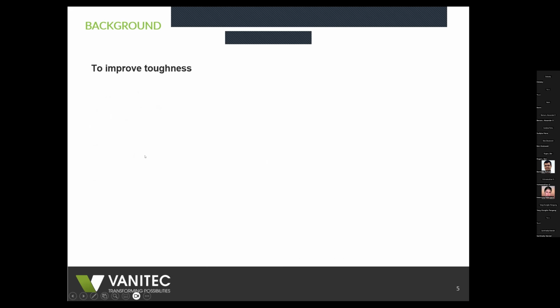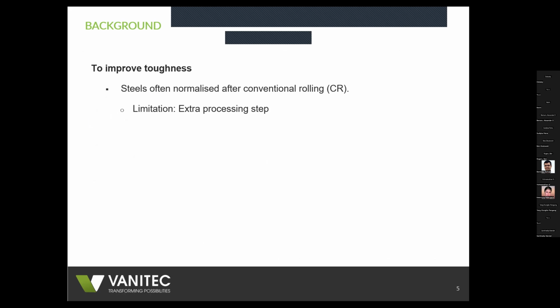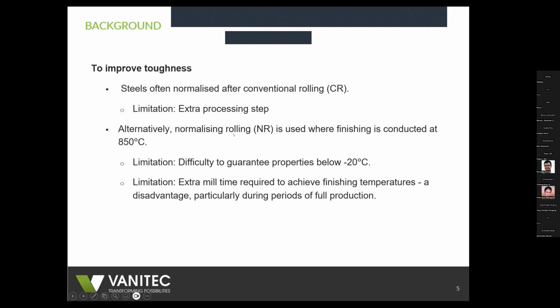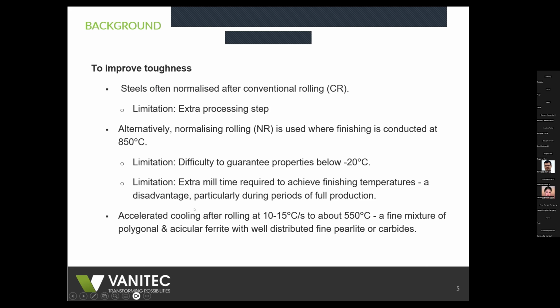You do get a relatively finer polygonal ferrite pearlite steel in the absence of the Widmanstätten, and with consequently superior toughness. Now, to improve toughness, just reverting back to the niobium steels, you would have to introduce an extra processing step. And also, of course, in the absence of controlled rolling, this is conventional rolling, you would have to normalize your material. Well, first of all, you'd have to either introduce controlled rolling, otherwise known as normalized rolling, where finishing is conducted at low temperatures. However, there is a difficulty to guarantee toughness properties below -20, and also you need extra mill time required to achieve these temperatures. So it's a disadvantage, particularly during periods of full production.